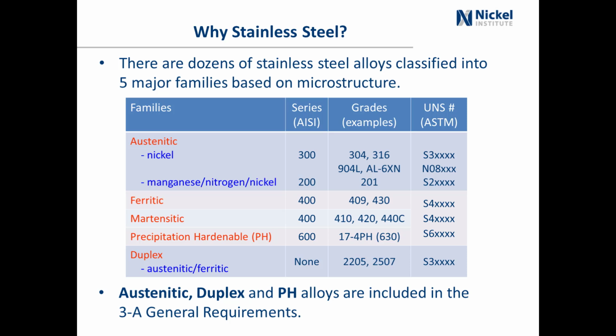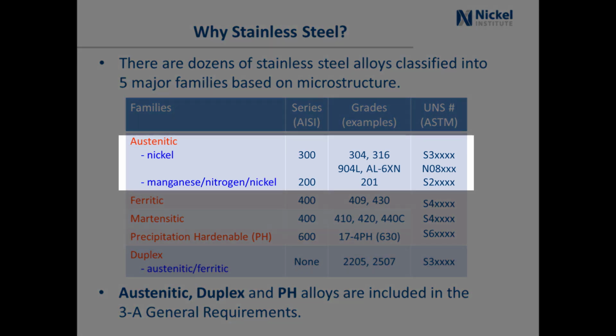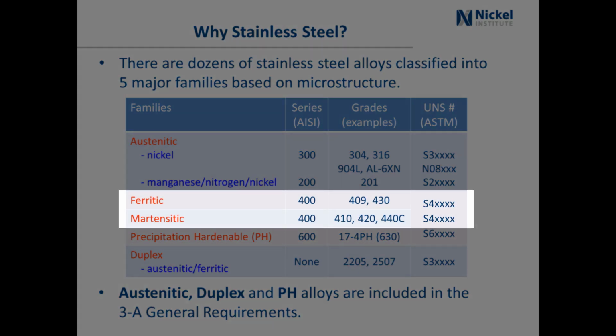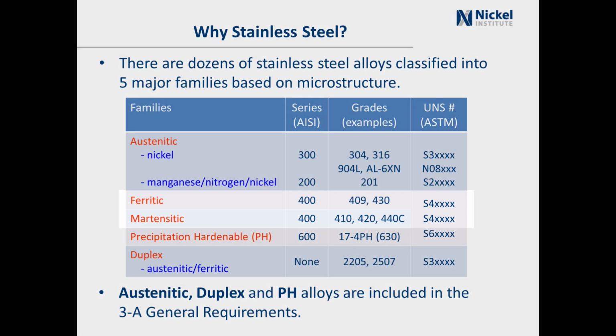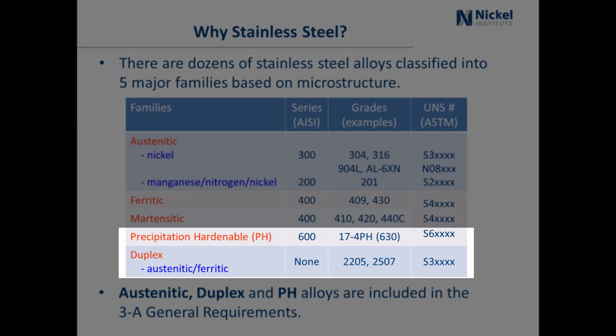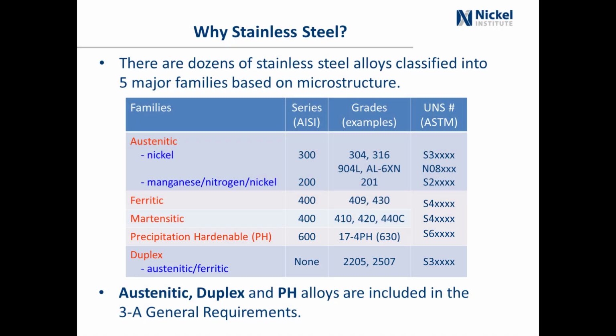And these 5 families are the austenitic family, the nickel-bearing ones, which include things like 304, 316, Al6XN, which is one of the 6% molybdenum alloys. There are ferritic, martensitic. Martensitic you would see like used in chef knives and that. Precipitation hardenable. And duplex. Duplex has a mixed microstructure, which is approximately 50% austenite and 50% ferritic, offers higher strength and better resistance to particular types of corrosion called chloride stress corrosion cracking, which I'll mention a little bit later. And so the austenitic, duplex, and precipitation hardenable alloys are listed in the 3A general requirements.